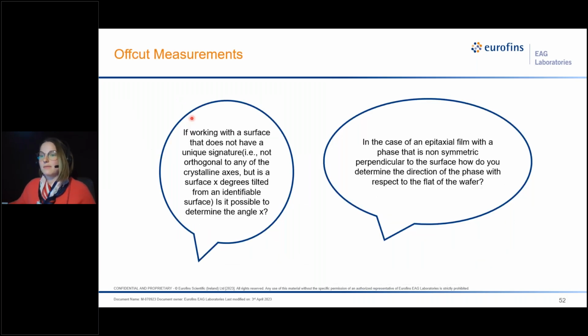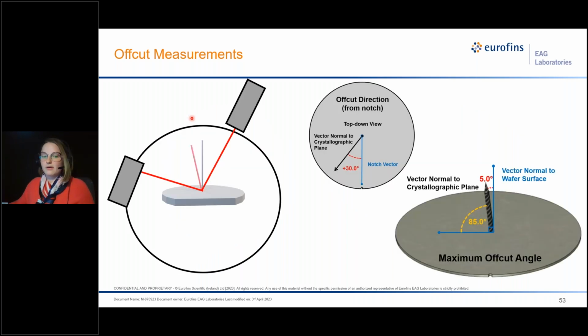And another question that people had was, if working in the case of an epitaxial film with a phase that is non-symmetric perpendicular to the surface, how do you determine the direction of the phase with respect to the flat of the wafer? So what these people are asking about is offcut. Now, offcut is very important for thin films because depending on the offcut of the substrate, it can actually affect how your layers that you put on top grow.